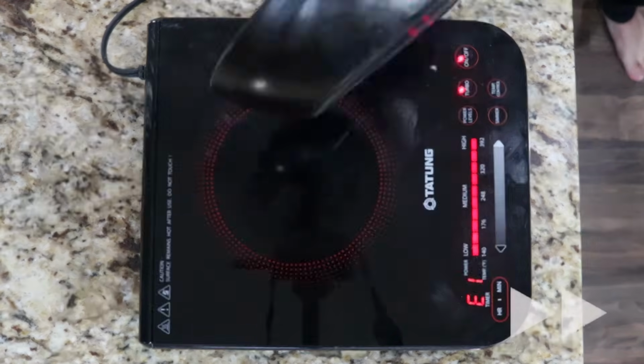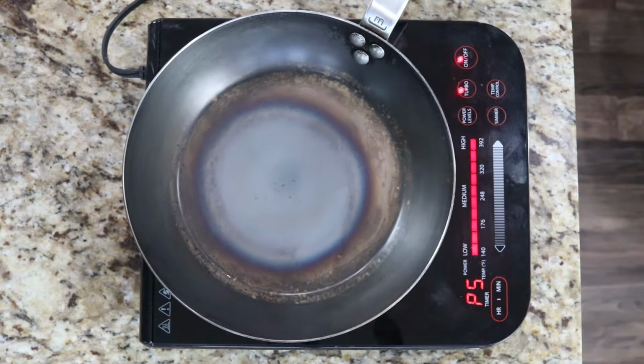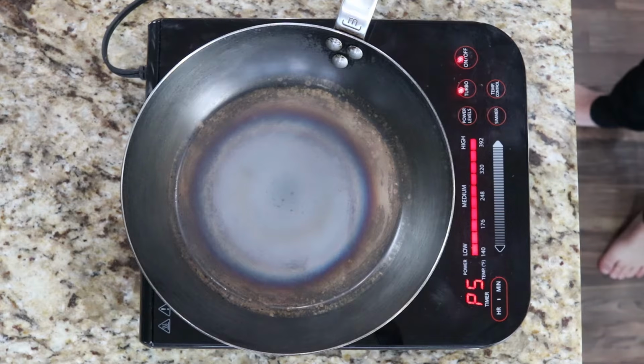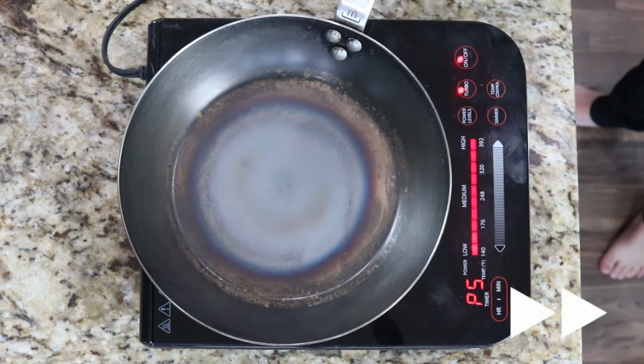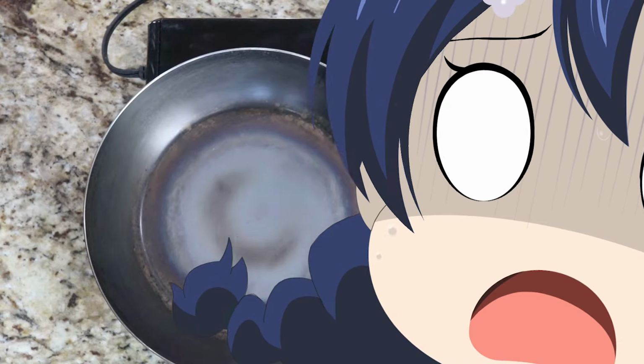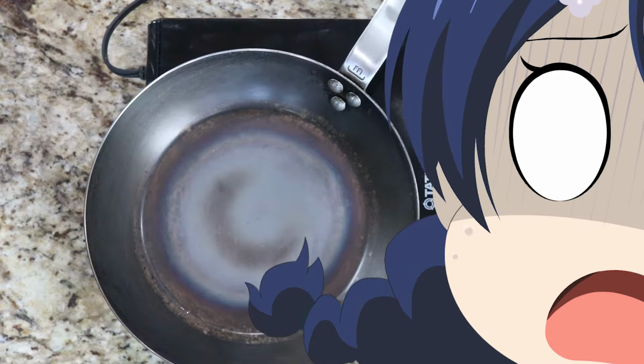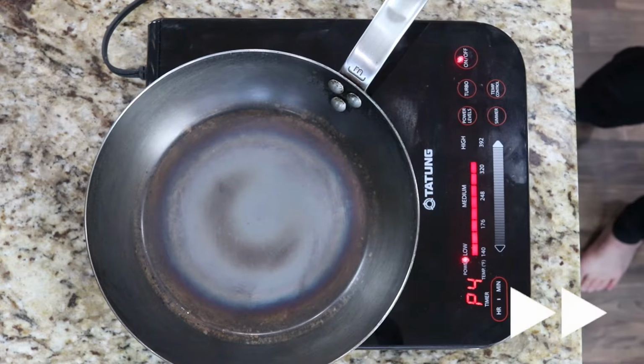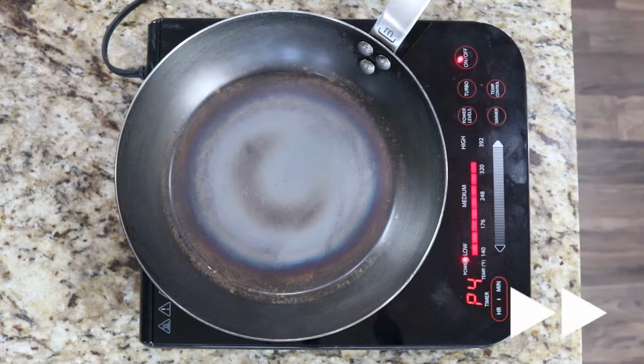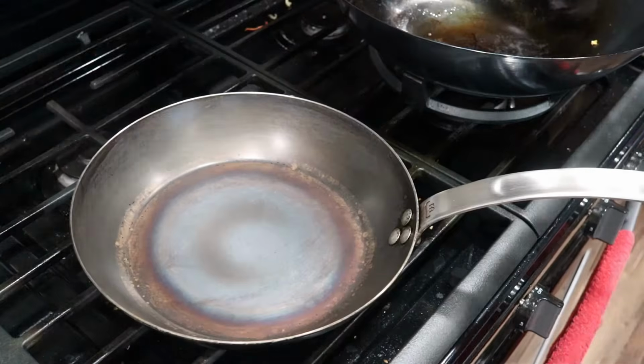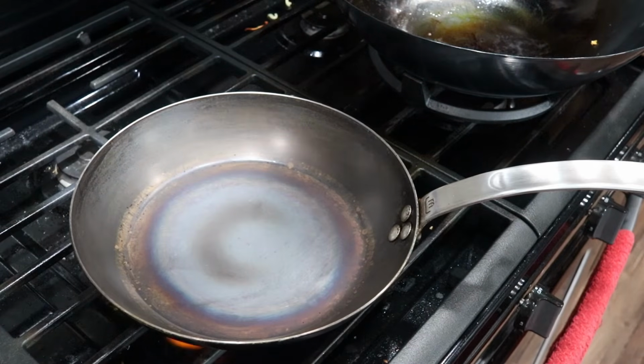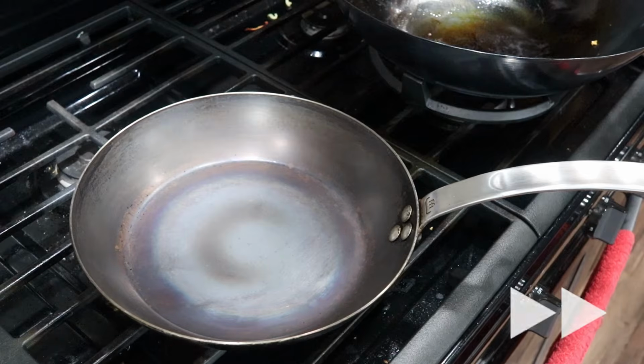If you're using a flat electric or induction cooktop, make sure to heat up your pan slowly and gradually to avoid warping the metal. This was my first time using an induction burner, so I actually accidentally warped this pan and the middle started bowing out. I let the pan cool down, and then it eventually returned back to almost flat, and I finished it off on the gas burner.